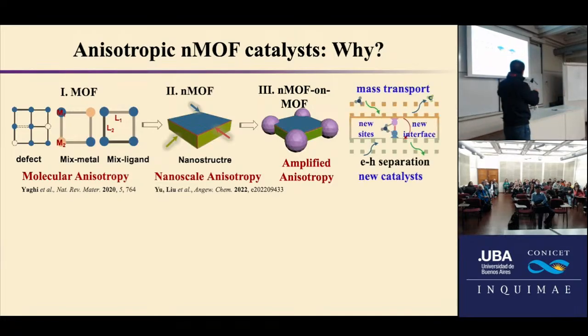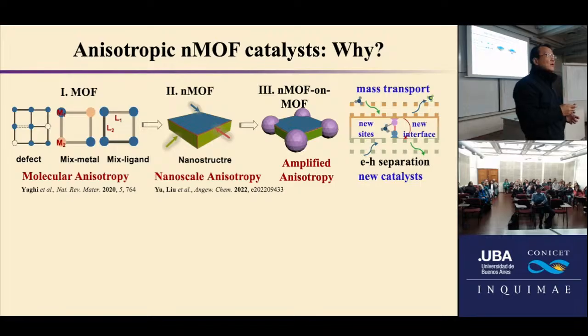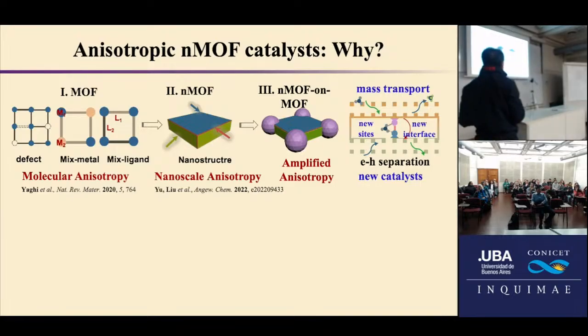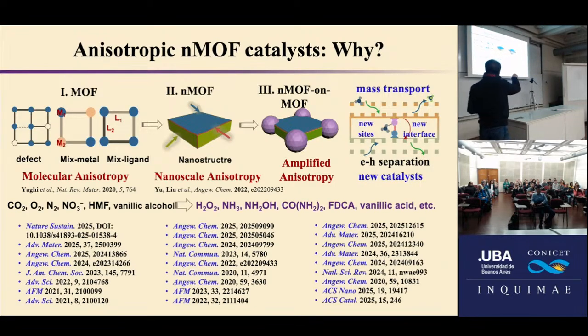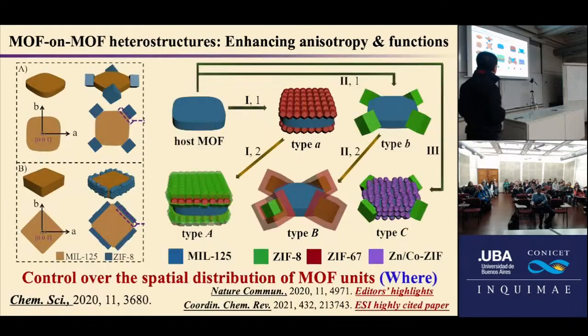And by doing that, the composition, facet exposure, etc., all the anisotropy and indeed the property can be amplified. And these are not just the combination of two old materials. Indeed, by doing so, you can create a new interface. At the interface, you can create new active sites. And they should be considered as new catalysts. So that is our design principle using anisotropic nanostructured MOFs, especially MOF-on-MOF materials for different applications. So I'll give several examples showing that.